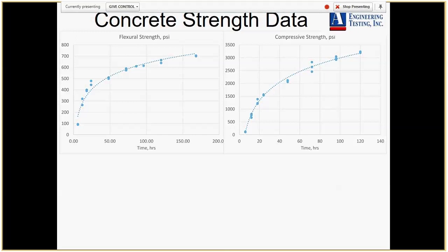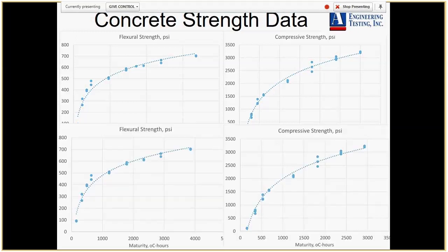interesting, because in the literature there is no agreement on which strength develops faster. About 50% of papers say that compressive strength develops faster, and another 50% say flexural strength. But it looks like in these mixes the flexural strength develops faster.